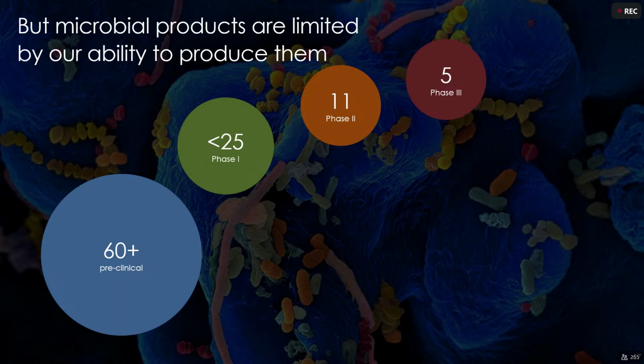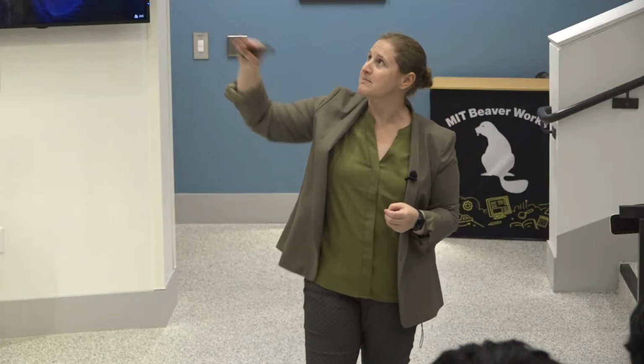So this is data from living biotherapeutics. That's a fancy word for microbes that would be FDA approved as medicines. Over 60 different microbes have gone to preclinical trials. Less than 25 make it to phase 1. For phase 2, you need at least a semi-final formulation. So you move from, in phase 1, they usually make people drink these in their native media, which is pretty gnarly, to phase 2, where they have to be dried. Very few actually can make it to phase 2. Phase 3, only 5 have made it, and none are currently FDA approved.